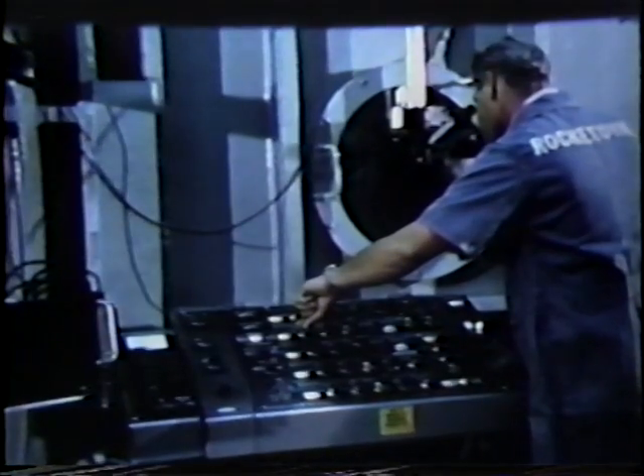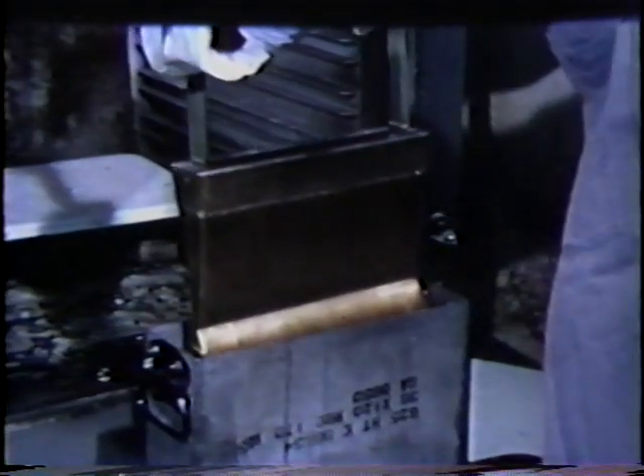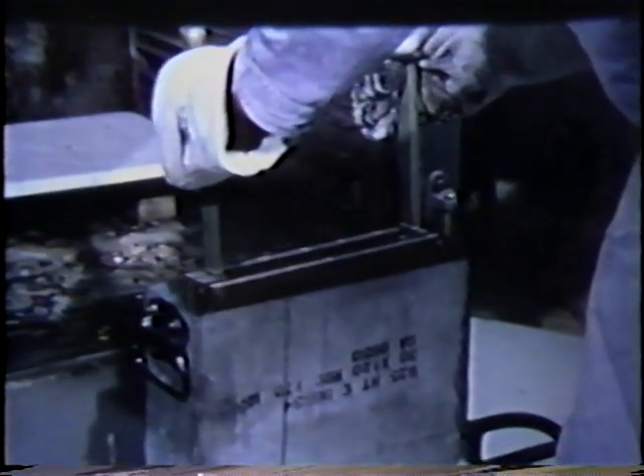Procedures developed through welding experiments ensure fissureless joints and produce the best crown and root surfaces. Uniform travel and beam power output produce less heat so that distortion in the parts being welded is minimized. This welded assembly is then prepared for electroforming of nickel to close out coolant channels on the outside of the liner casting.